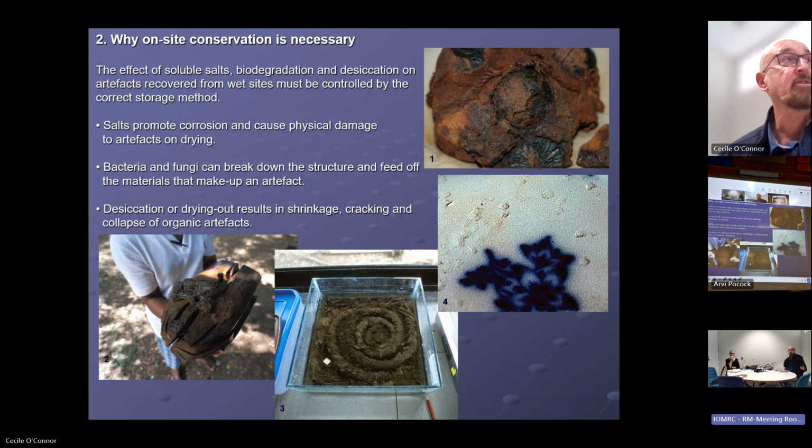So obviously the thing is in a certain condition when we find it. Once we bring it out of the water, we need to keep it wet, so it goes directly either into seawater or fresh water, whichever is appropriate. If we allow that to dry, the salt in those objects will actually crystallize, and that can cause damage as well. Not only is it hygroscopic and attracts moisture from the atmosphere, which promotes corrosion of metals, it also can destroy it physically.